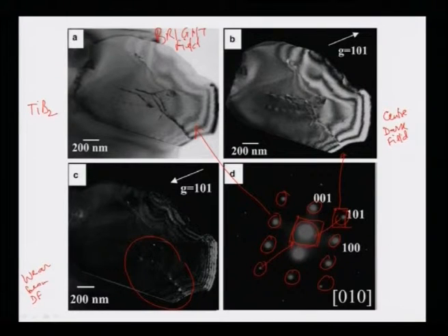The reason is this: in a center dark field image, the whole grain is illuminated strongly because it is diffracting strongly. Therefore, the defect structure cannot be seen so nicely. On the other hand, in a weak beam dark field image, you can easily reduce the intensities because you are bringing the strong parts to the central position. Therefore, you can create a much better image. So, this is in a nutshell what is done routinely in a conventional microscope.